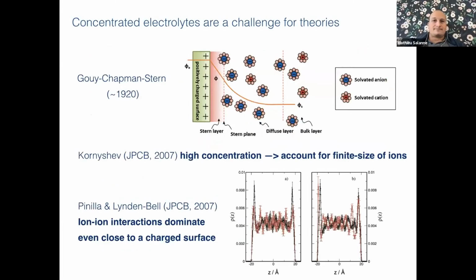One problem for theory is that we are dealing with concentrated electrolytes. And in fact, the main theory that was used and still used is the Gouy-Chapman theory that tells you that you have a strongly adsorbed layer and then a diffuse layer. But in fact, this theory works only up to concentration of 10 to the power minus 3 mole per liter. And this picture that we always use is wrong because, in fact, such concentration corresponds to 1 ion pair every 100 of thousands of water molecules. As soon as you increase the concentration, it doesn't work anymore because you have strong correlation between the ions, they attract each other, and so you cannot use this picture in principle.